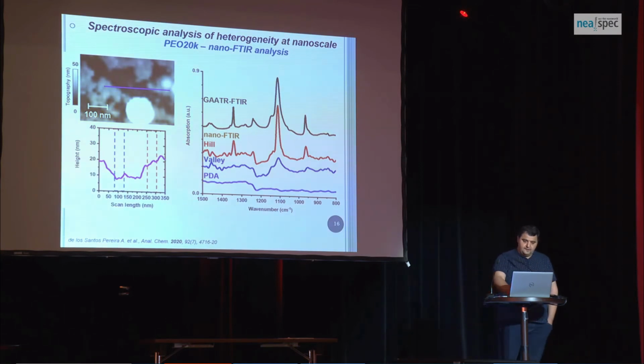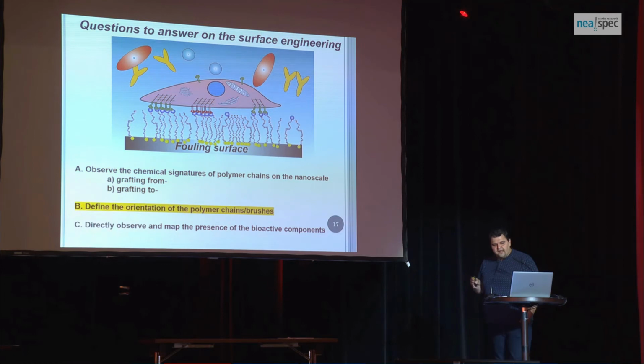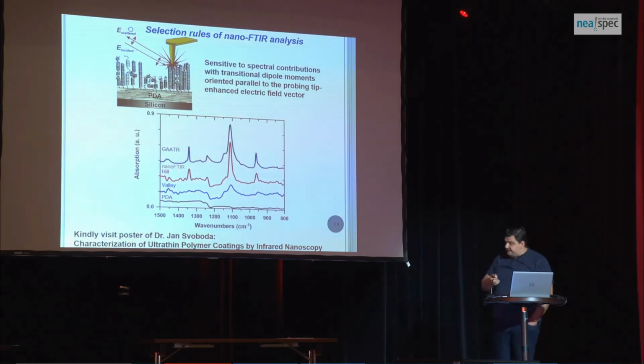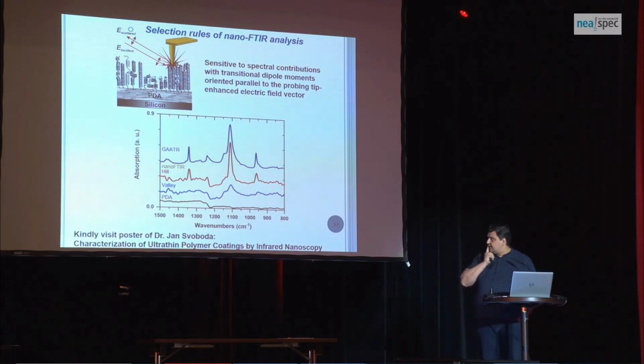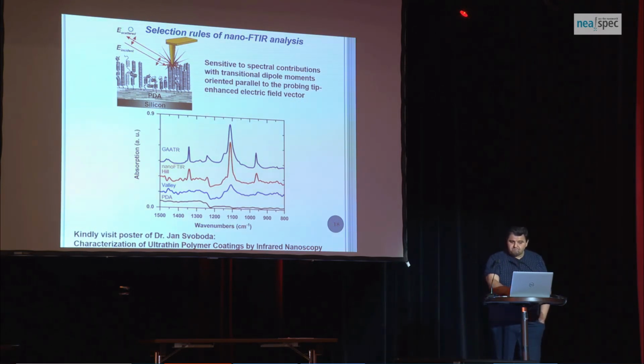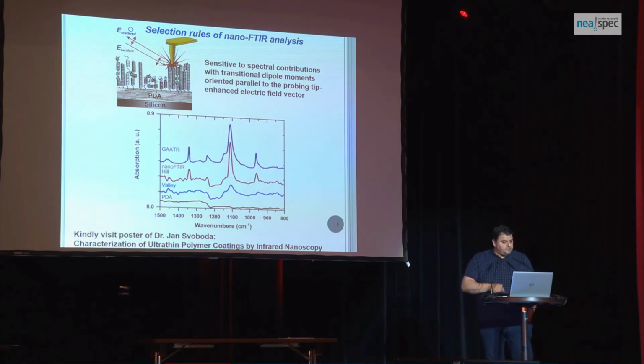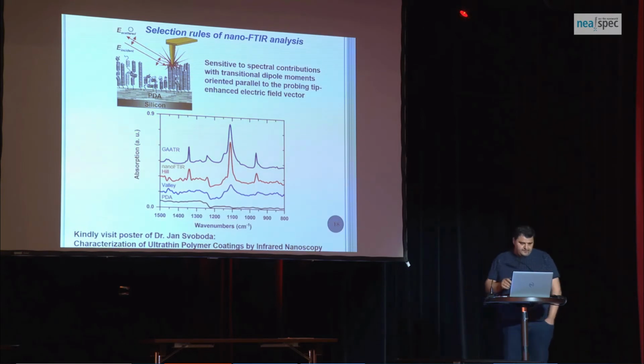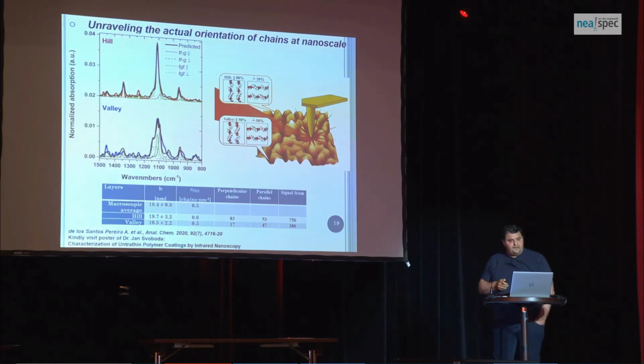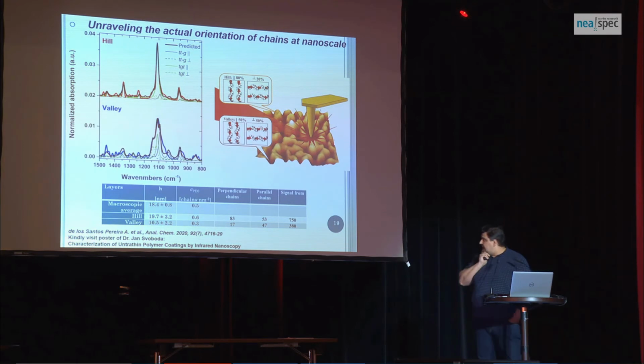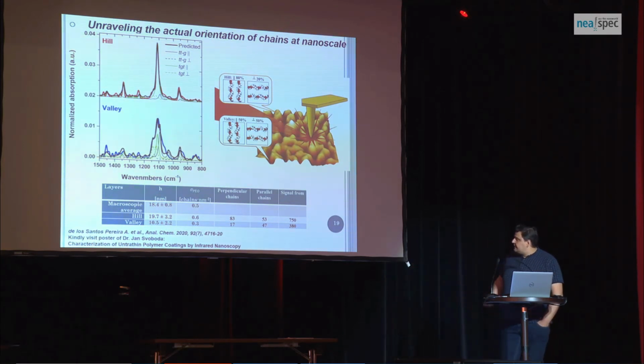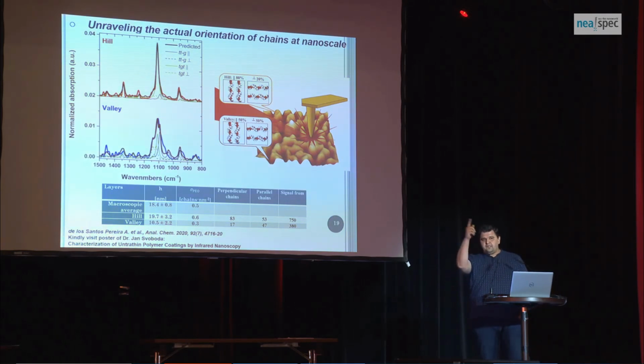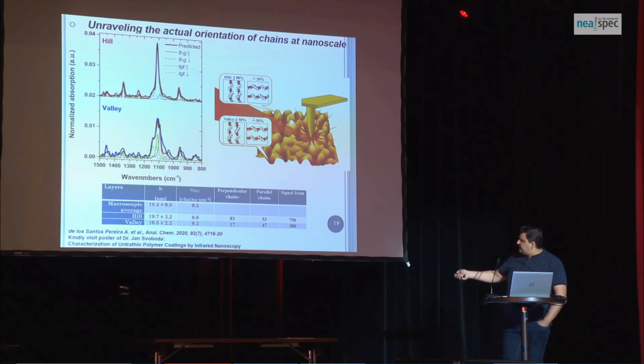We pushed even further. So we said, let's see, and define the orientation of the polymer brushes. So please visit the poster of Dr. Jan Svoboda. We can talk more about how we did the orientation and so on. Basically, we took into account that we are sensitive to the spectral contributions with transitional dipole moments oriented parallel to the field. We did some calculation. We optimized the most energetically favored conformers, we calculated their infrared spectra, and voila. What we got is that in the hill region, most of the chains are perpendicularly oriented to the surface, whereas in the valley we have something like 50 to 50%.